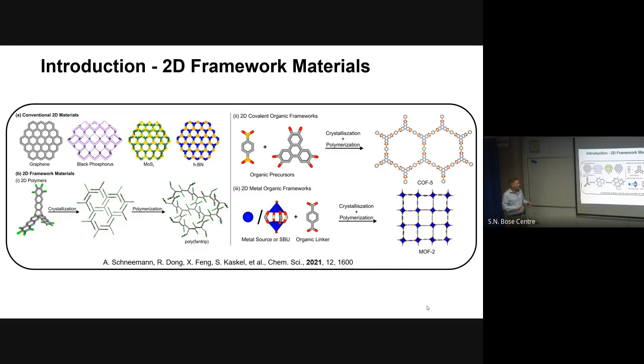For the 2D materials, you have first the crystallization process. So you have, for example, these triptycene units, and they align first into a crystal, and then they are polymerized. And then you still have measurable single crystals, for example, of this material. And then you can exfoliate them.